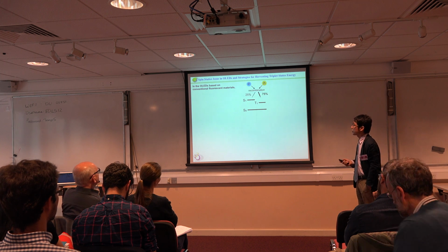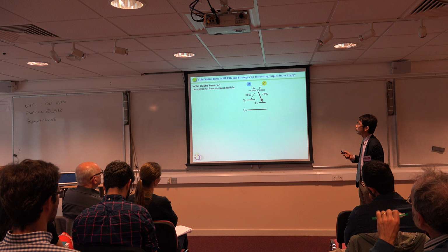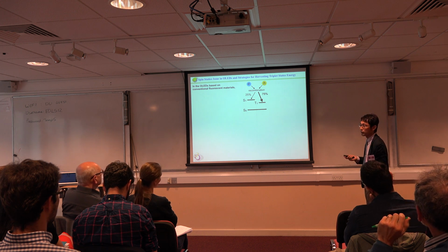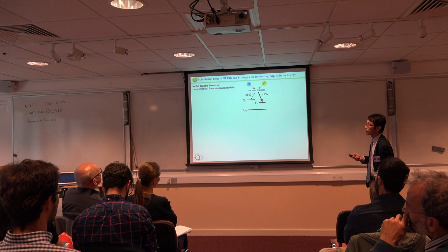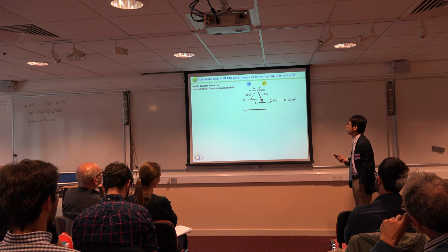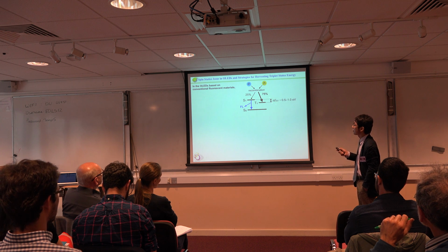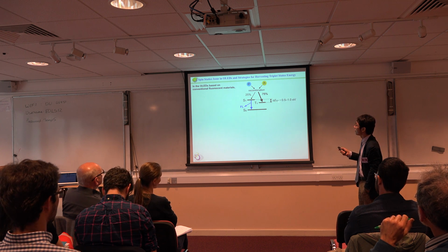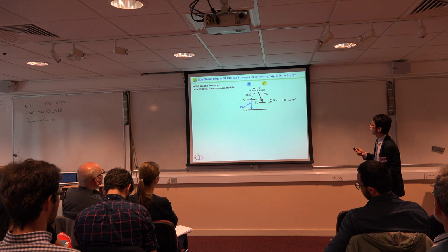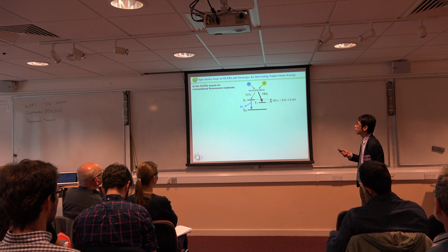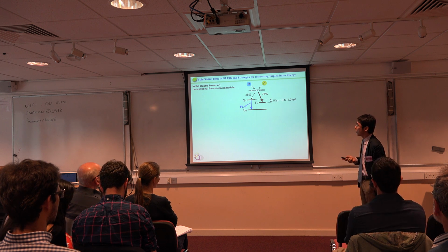Especially in OLED devices, the electron and hole combine to generate triplet and singlet excitons in 75% and 25% respectively. However, usually with conventional fluorescent molecules, with a delta EST of maybe 0.5 to 1 eV, only the singlet state emits the light.